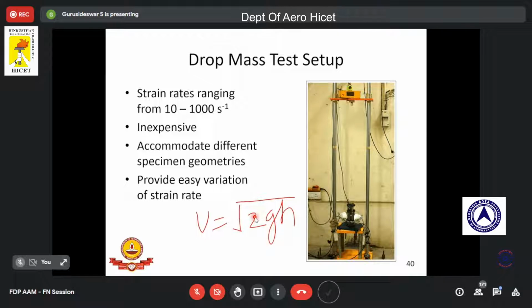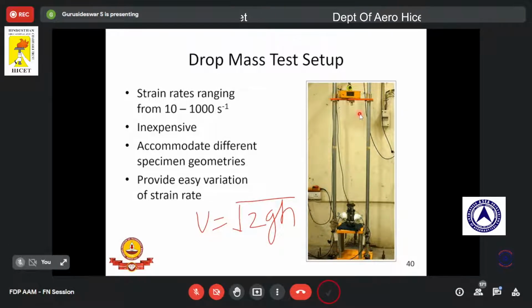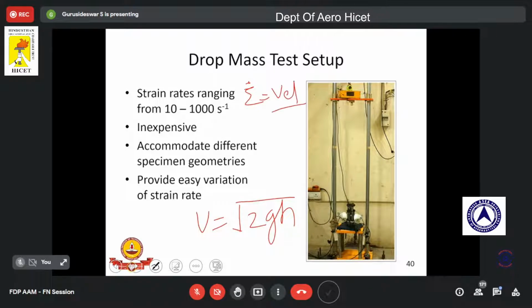Different velocity leads to different strain rate. So we chose 3 different heights, say 0.5 meter, 1 meter, 2 meter, like that. By dropping the mass at different heights, we get different velocity, and different velocity will lead to different strain rate. As I told you earlier, the strain rate is nothing but the velocity over the gauge length. So this is the strain rate, and this is what we achieved by using this drop mass setup.